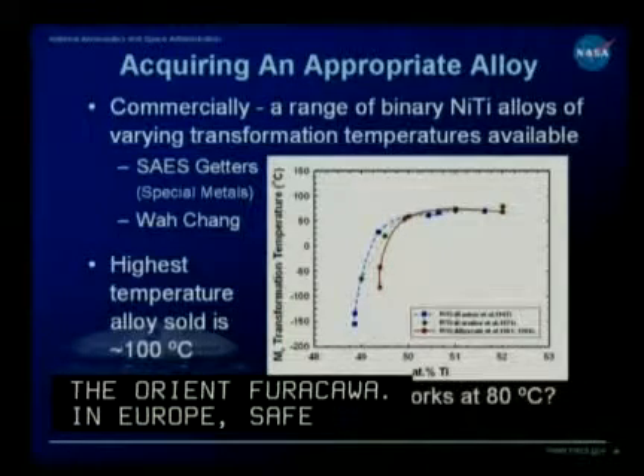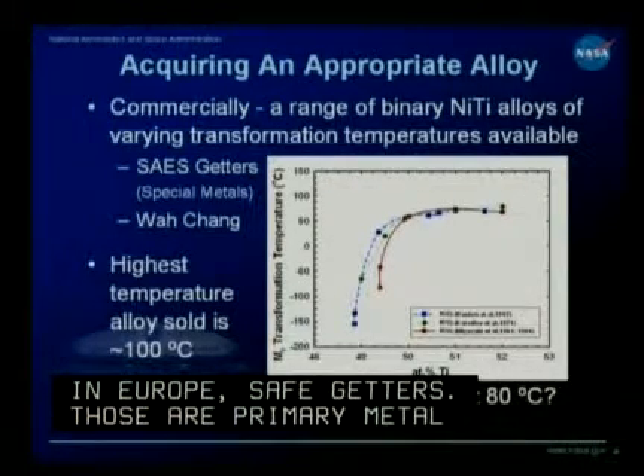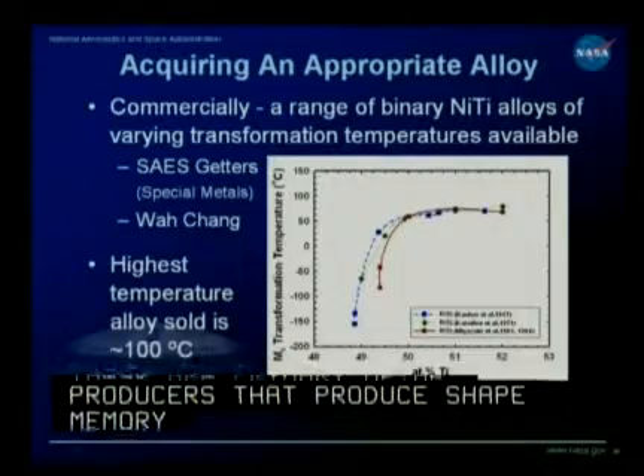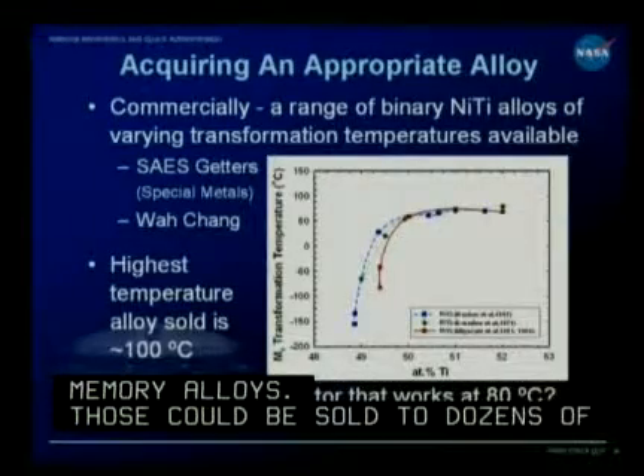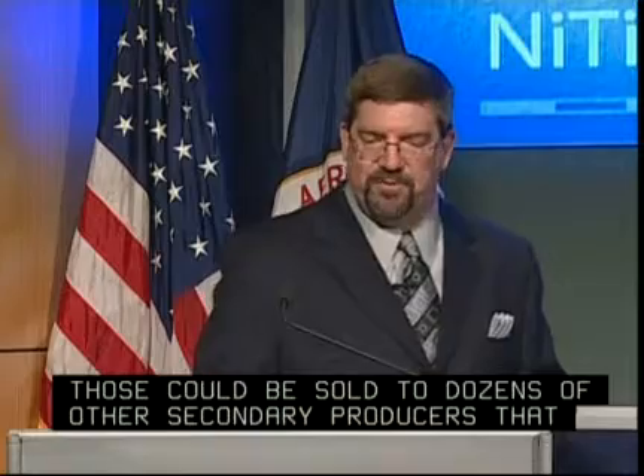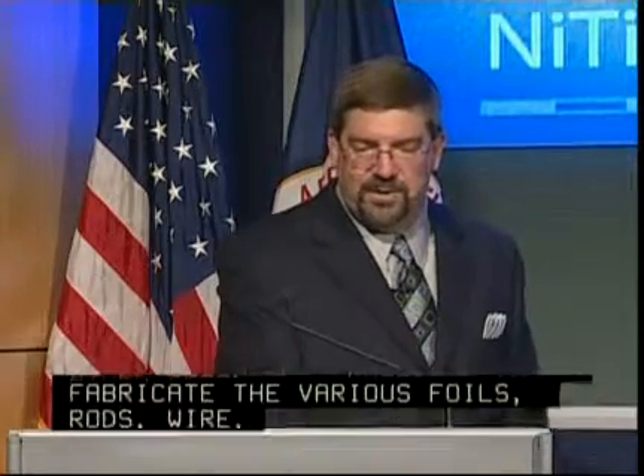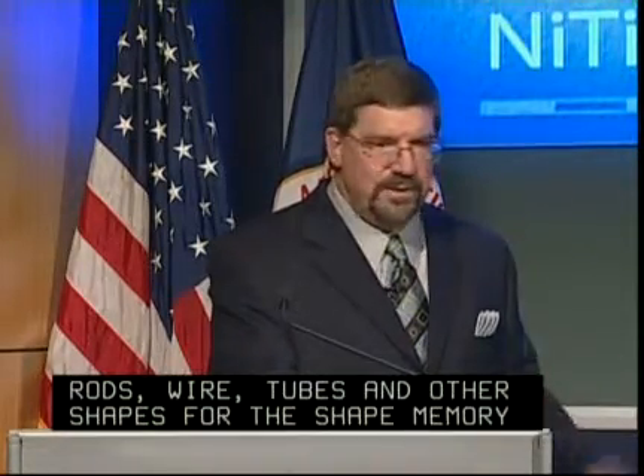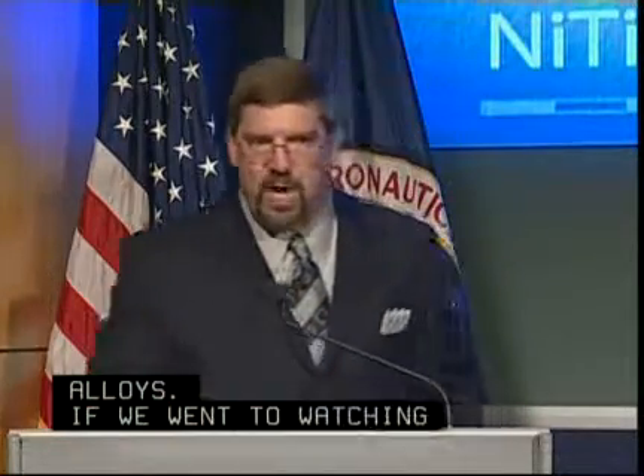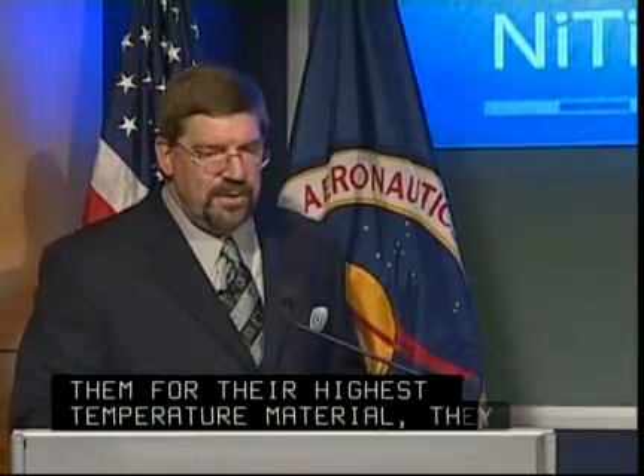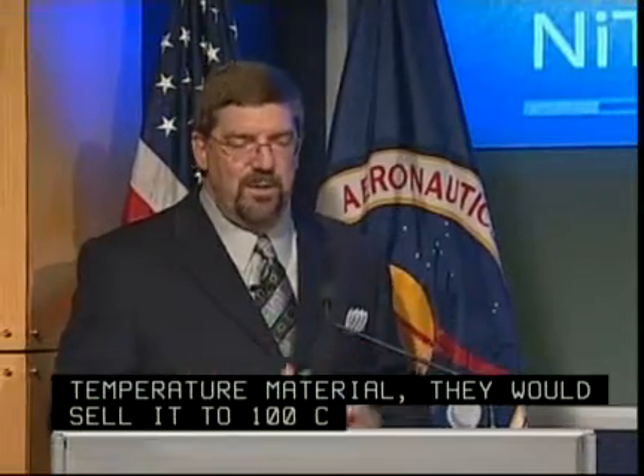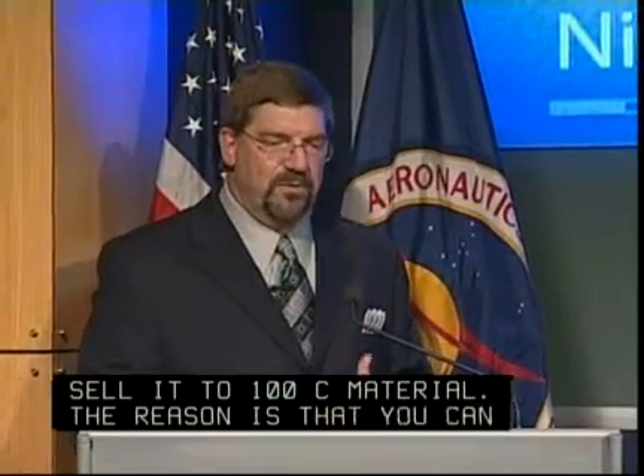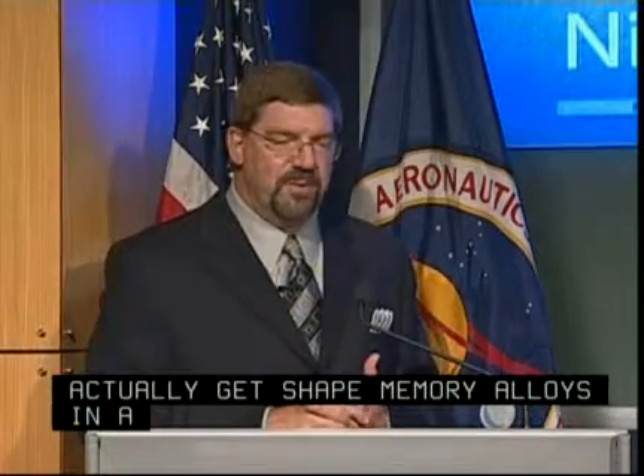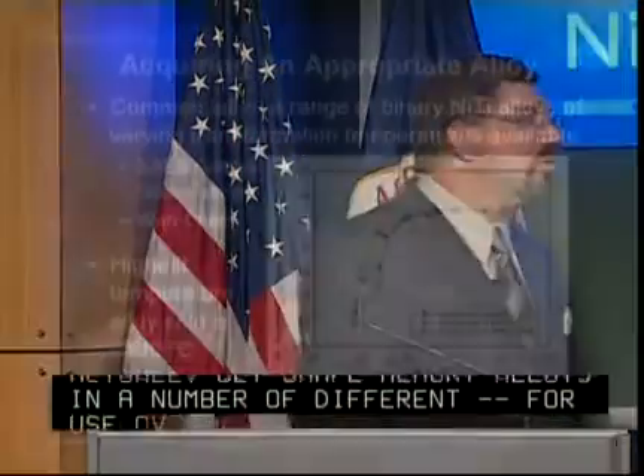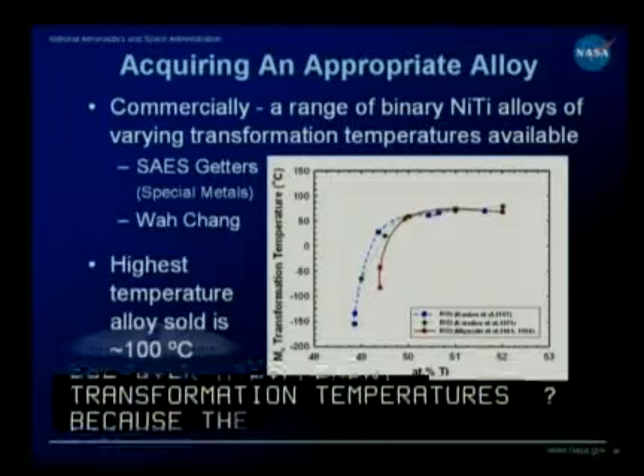Those are primary metals producers that produce the original ingots of shape memory alloy. Those can be sold to dozens of other secondary producers that then fabricate the various foils, rods, wire, tubes, and other shapes for the shape memory alloys. But if we went to, say, Wah Chang and we asked them for their highest temperature material, they would sell us 100 C material. Now, the reason is that you can actually get shape memory alloys in a number of different compositions for use over different transformation temperatures, because the transformation temperature itself is a strong function of stoichiometry.